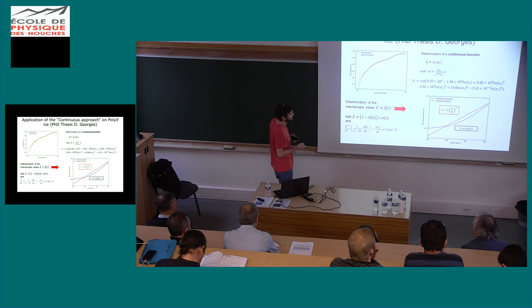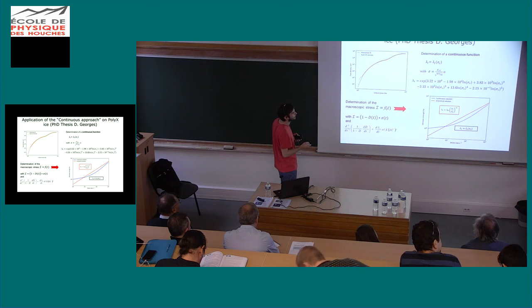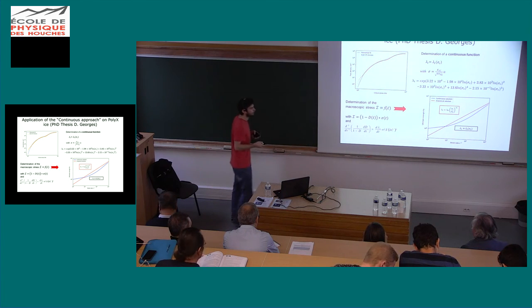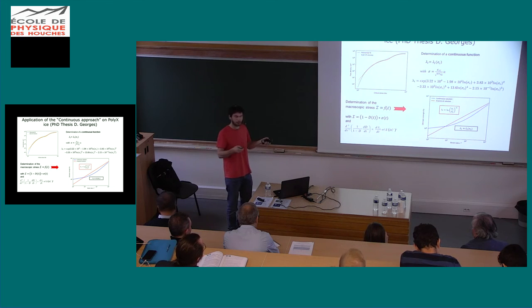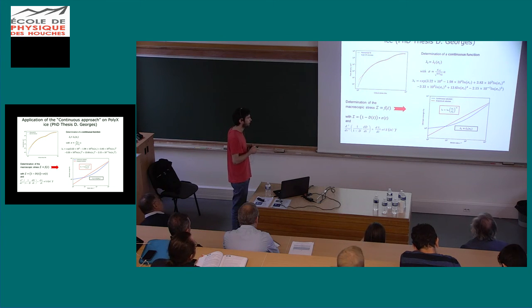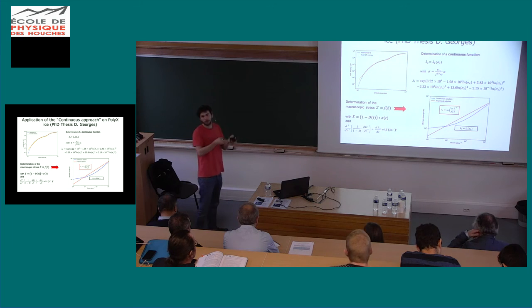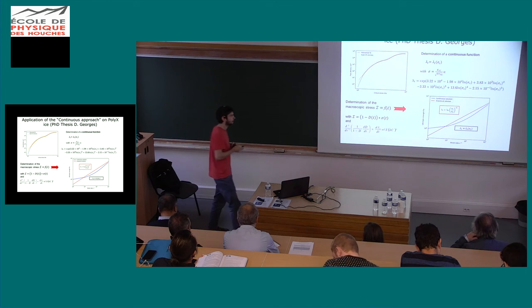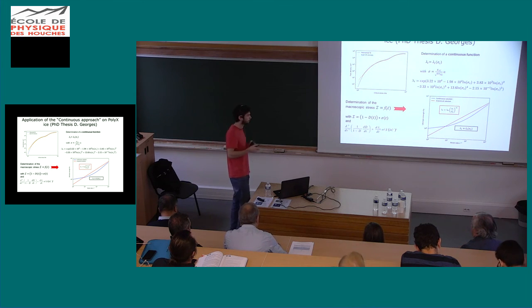Eventually, at higher strain rates, we will see, like Maria, a shift in the behavior of the continuous solution and the analytical solution. But the resolution of the volume we used was too low to get to higher strain rates. So for higher strain rates, we should use a smaller volume with a better resolution to actually get smaller porosities.